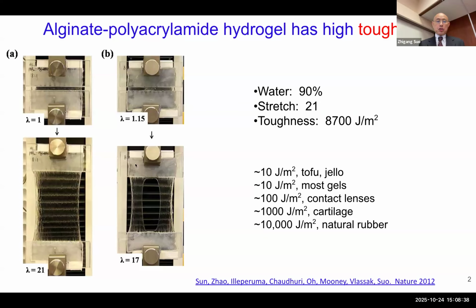So I already mentioned it can be stretched 21 times and contains 90% water. Now, for this number, many of you may not appreciate how gigantic it is. So just compare with a number you are familiar with. Tofu, jello, about 10 joules per meter squared. 10 joules per meter squared is a pretty tough tofu. If you have tender tofu, the value is even lower. So most gels people prepare in the lab are about 10 joules per meter squared. So we're talking about several orders of magnitude difference.